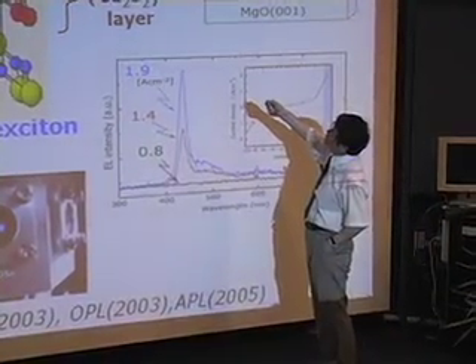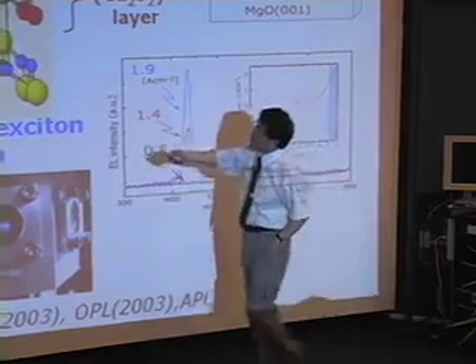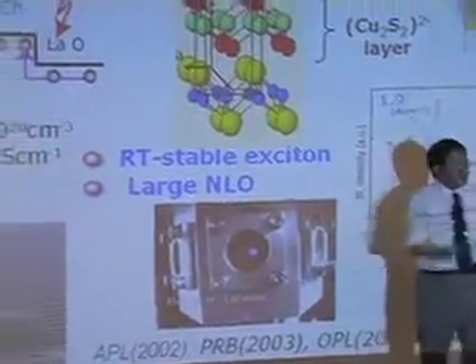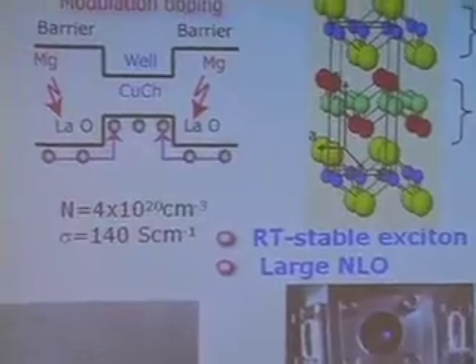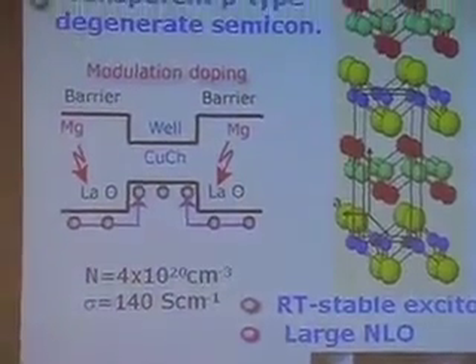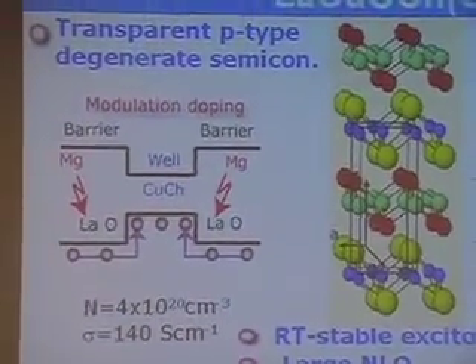When lanthanum is replaced by a divalent cation, a hole is injected. But due to the band offset, the hole moves from here to here. The impurity is here, but the hole is located here, so we can avoid hole-impurity scattering, meaning we may expect large mobility.